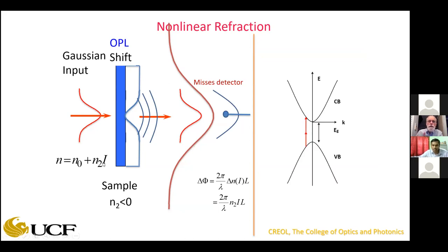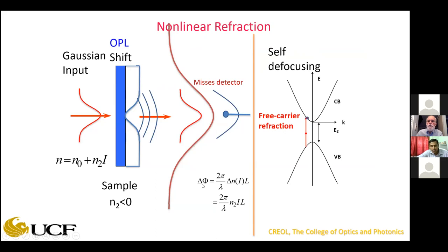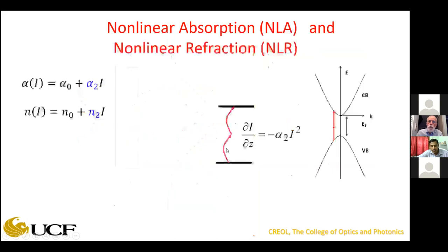The way you get negative nonlinear refraction is that when you have two-photon absorption, you create free carriers — excited carriers — and you're above resonance for those carriers. That causes self-defocusing. It's not a simple n₂; it's actually a higher-order nonlinearity, but it gives you a very large nonlinearity, especially for long pulses. That's just one of the mechanisms causing those early overestimates.